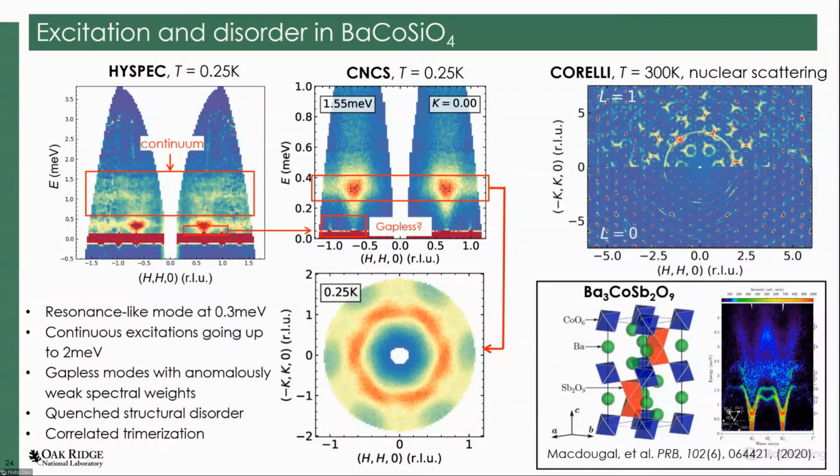The structural diffuse scattering also follows chirality. If we plot HKL space in reciprocal space, at L equals 0 we don't see much diffuse scattering, but at L equals 1 we see it. That means the diffuse scattering may be related mostly to out-of-plane displacement. We did a single crystal X-ray with structural refinement. If we only consider the Bragg peaks, we notice some atoms need to be split.